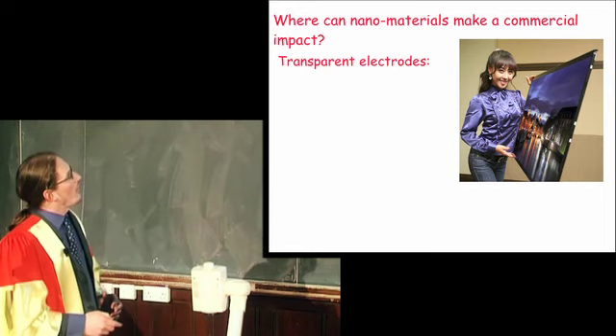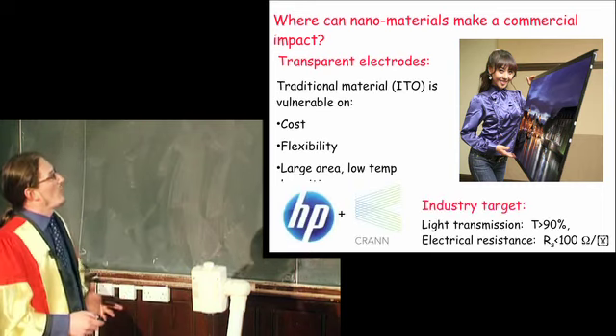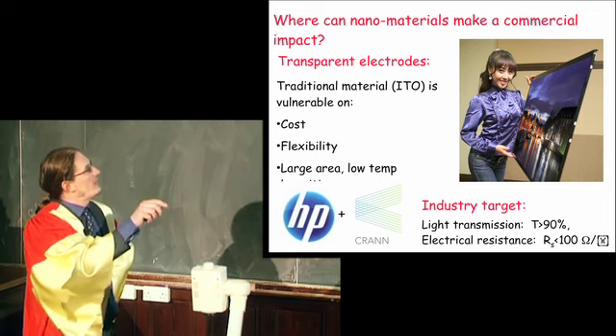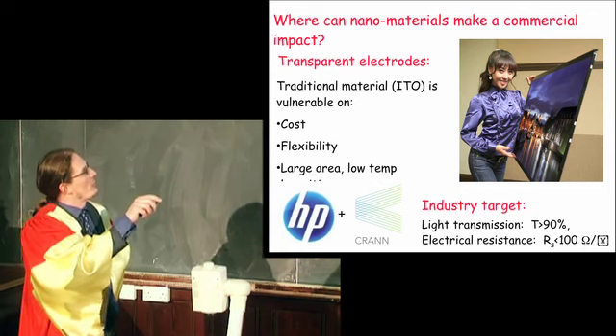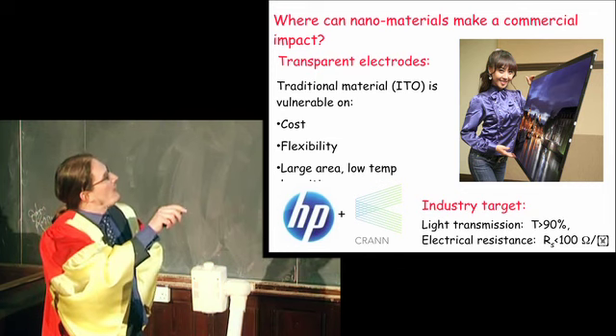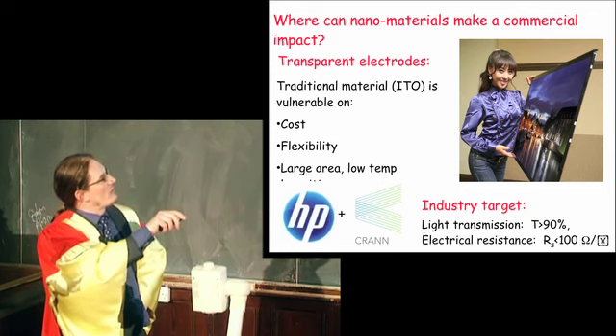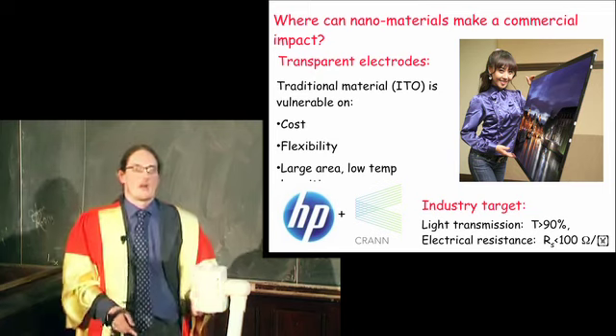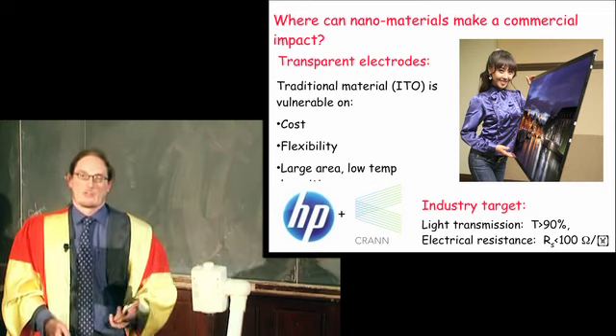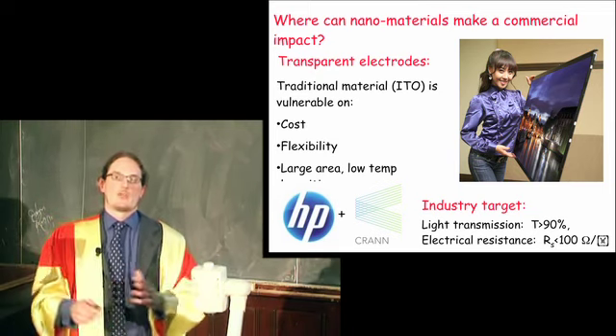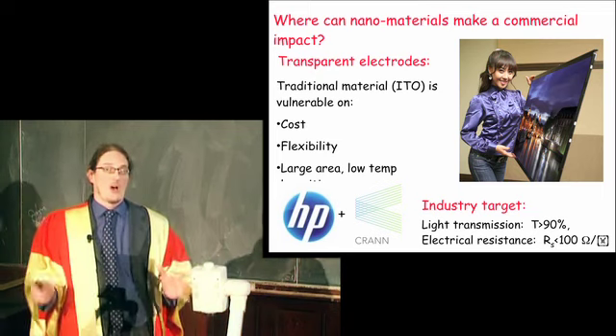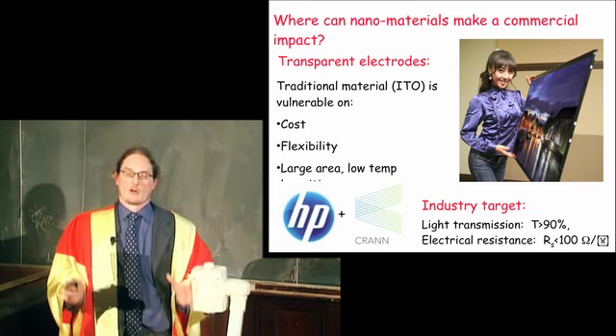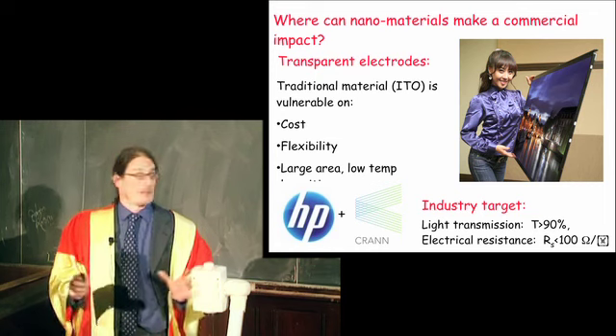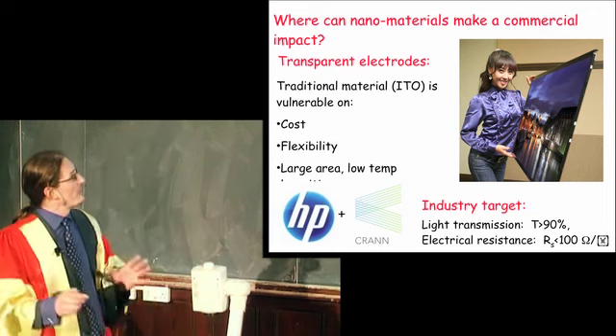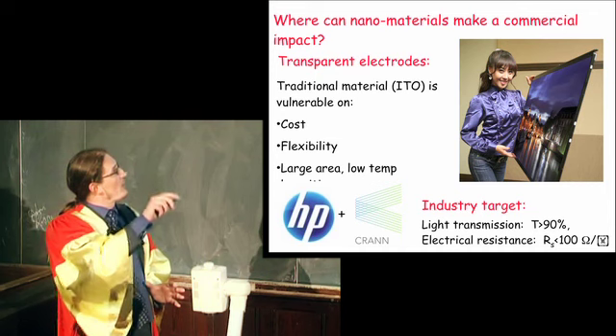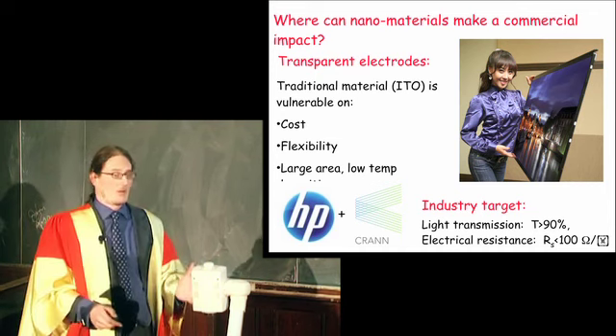Well, it turns out that there are a small number of metals that are transparent. Indium tin oxide, a conductor is probably a better word to use, is a conductor that's transparent and is used traditionally here. Now, one of the problems with indium tin oxide is that indium is running out. We expect that we will have depleted almost the entire global supply of indium at current rates in 25 years. Now, that I think is actually worrying. But in any case, that means the cost of indium is rising, and that's not good for industry.